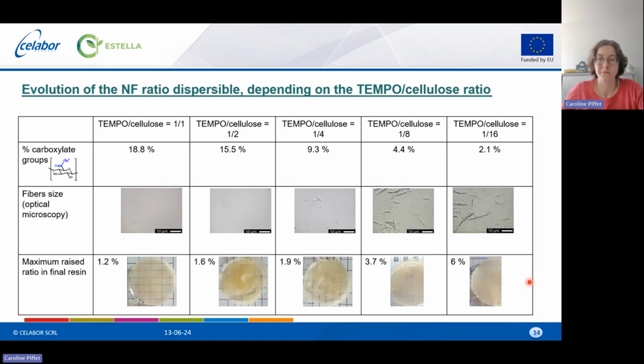Then still on the characterization of those different celluloses, you can see also that what we just saw in the viscosity and UV spectroscopy is confirmed by the observation with optical microscopy. You can see that with high ratio of functionalization, we don't see the fibers in the optical microscopy, but these are bigger and longer and thicker with low functionalization ratio. And then still on the commercial resins, we try to see the maximum ratio of nanofibers that can be included in that system. And you can see that for the very thin nanofibers, we could go up to 1.2% of nanofibers. And for the longer, we could go up to 6%.